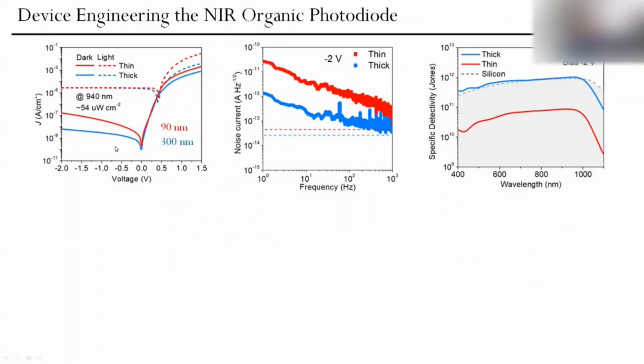So we made two types of devices, one with a thin active layer, one with a thick active layer. And we see here the noise current as a function of frequency. It is actually related to specific detectivity, which shows the ratio between useful signal and electrical noise. And we see that with increasing thickness of our active layer, we can significantly increase the specific detectivity of our organic photodiode, which becomes comparable to the specific detectivity of a silicon photodiode.